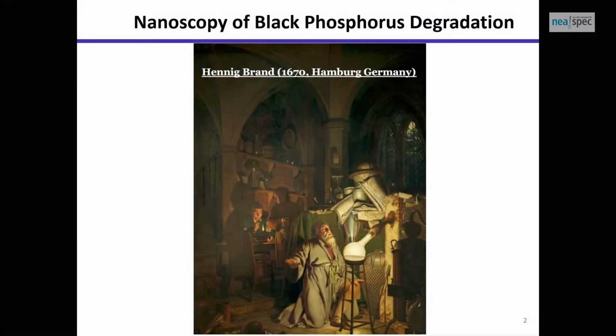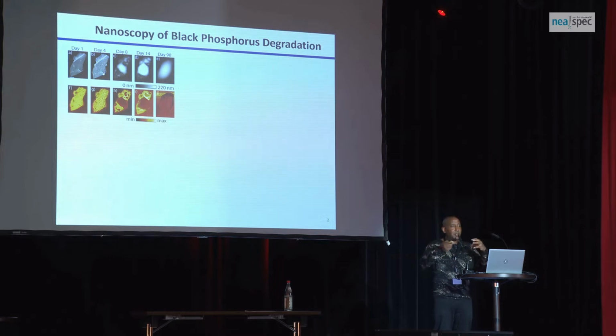It's a very reactive material. When you have a phosphorus material, for example black phosphorus, all the phosphorus atoms have these lone pairs, these free electrons, to interact. As a result, it's extremely reactive. And those of you who worked with this material know that as soon as you put it under your SNOM, in the beginning it's okay, it looks nice, and then literally a few minutes later it starts to form bubbles, and these bubbles start to grow and connect, and then you have a different material in effect pretty soon.